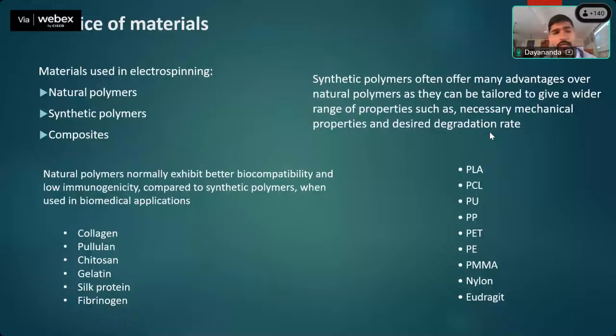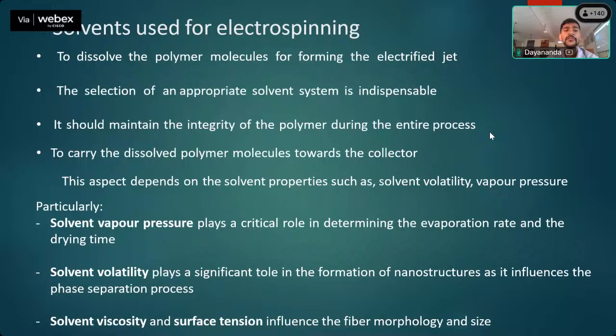Once you decide the polymer, the next step is to select the solvent. This is very important - we have to select the solvent carefully, because it must dissolve the polymer completely, which is mandatory. Even a small particle that is not soluble, or only sparingly soluble during dissolution, can cause problems. Imagine the electrospinning setup with the needle connected to the syringe - the needle diameter is very small, so even the smallest undissolved particle can block it. That's why we must choose a solvent that dissolves the polymer completely.